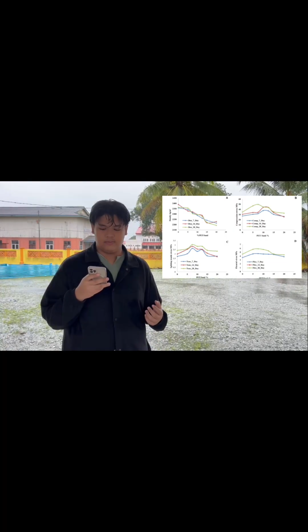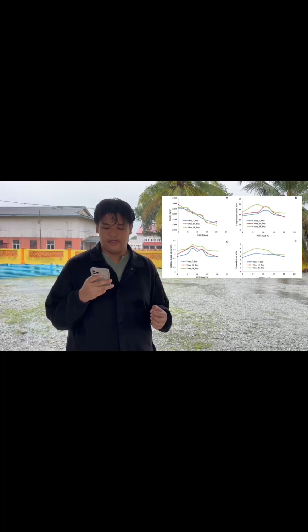Tests on raw PET particles are used to ensure the particles meet the requirements for sand under the standards and ASTM specifications, such as specific gravity and absorption rate, to understand the physical properties of the PET particles compared to natural sand. Tests on fresh and hardened concrete: the slump test is performed to evaluate the workability of the fresh concrete mixture.